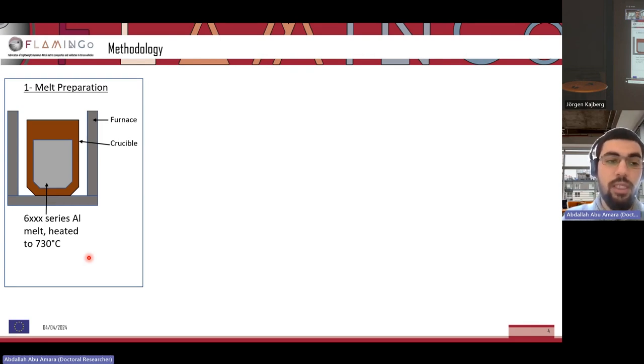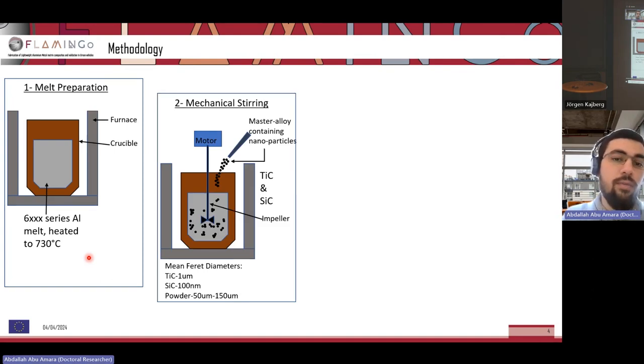So essentially we heat the 6000 series alloy to 730 degrees in an electric furnace. Then we can add the master alloy containing the nanoparticles. So we wrap the powder in foil, and as you can see, we pour it directly into the melt. So this would be the powder containing nanoparticles. And during this action of pouring the powder into the melt, we apply mechanical stirring. So essentially we have a rotary device connected to an electric motor, which stirs the melt, if you like, and kind of aids with the introduction of the particles into the melt and with the dispersion as well.